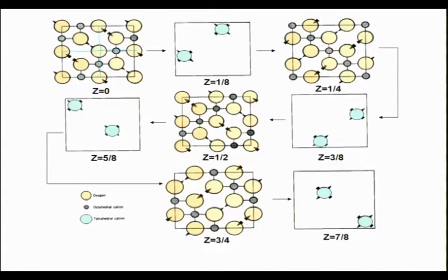You are going to have 8 of these. So 4 on the top, 4 on the bottom, 4 on the bottom, 4 on the top. Now within these you start filling the octahedral sites first. You can see that this is an octahedral site, edge centers are octahedral sites, right. But you don't fill all of them, you fill only half of them, because octahedral site occupancy is only 50%. So this is an octahedral site, you fill. You cannot put them randomly, you have to put them in a fashion so that you end up making a periodic unit cell.